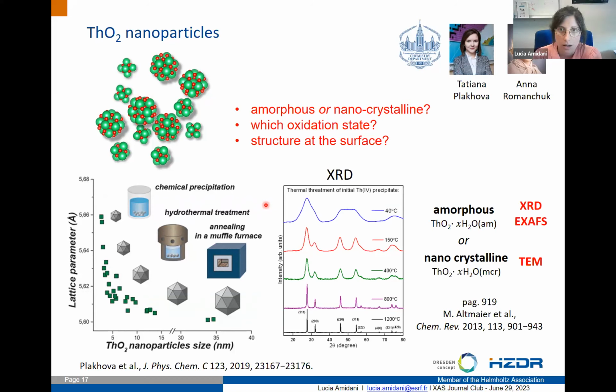Are they amorphous? Are they nanocrystalline? This is a nice review for the thorium dioxide case. I would say it depends a lot on which technique we use to look at those samples. If we go for XRD and EXAFS, typically we would say more amorphous because of certain things. But for example, if we look at EM, we see some fringes.